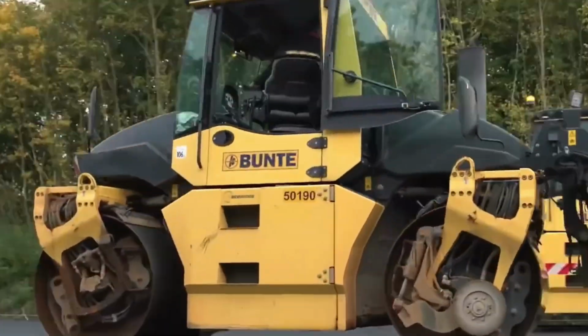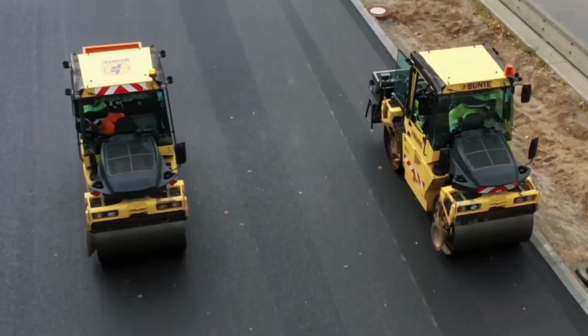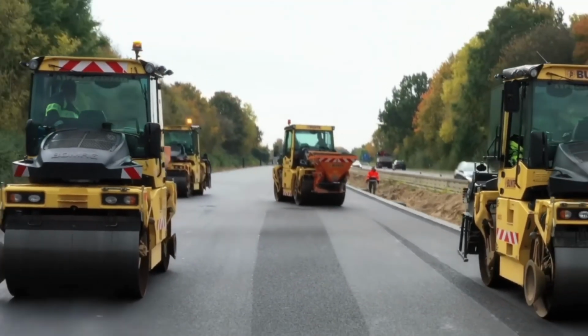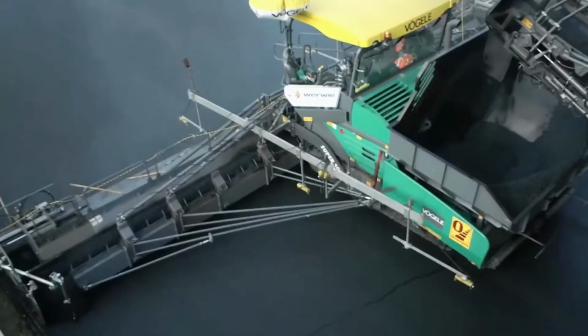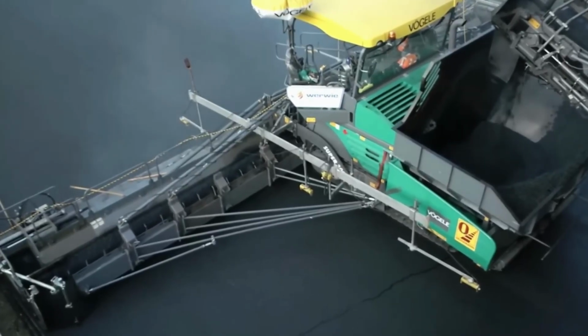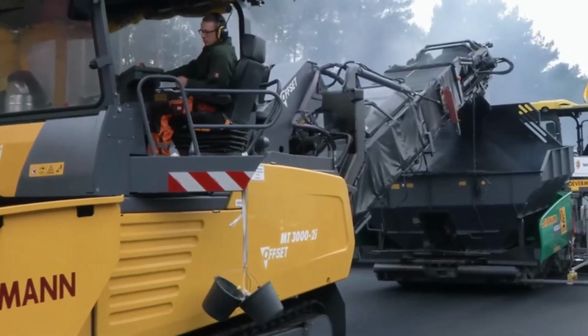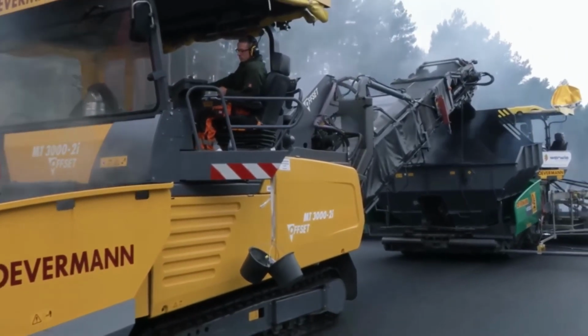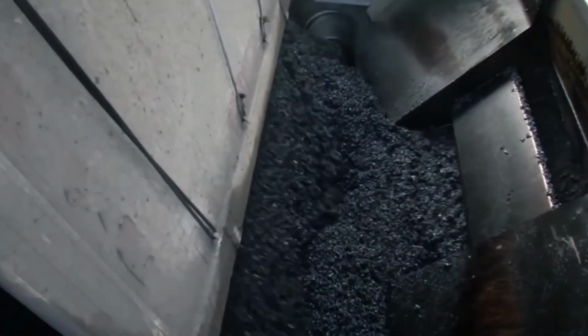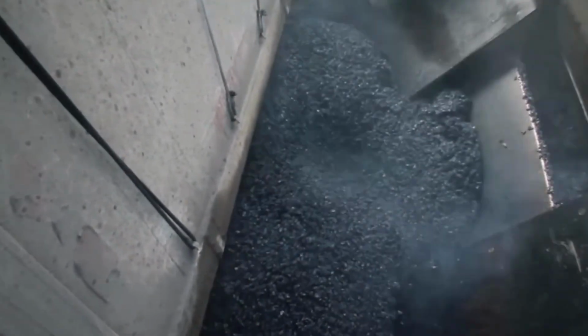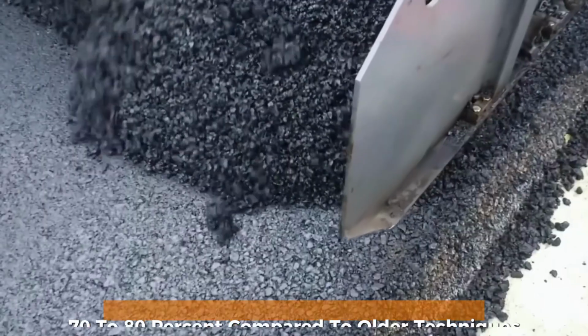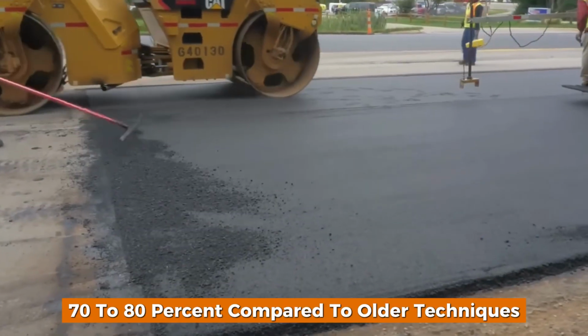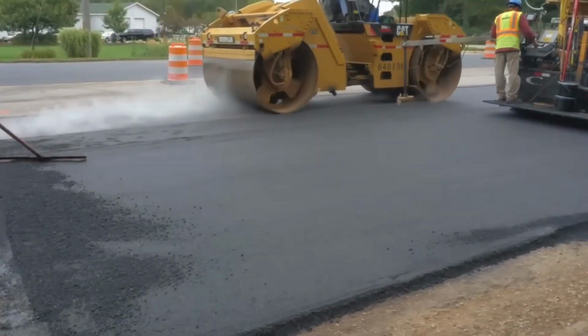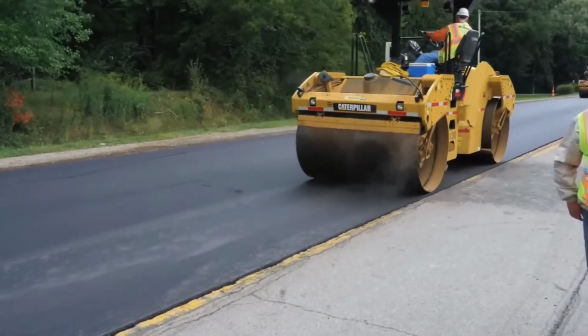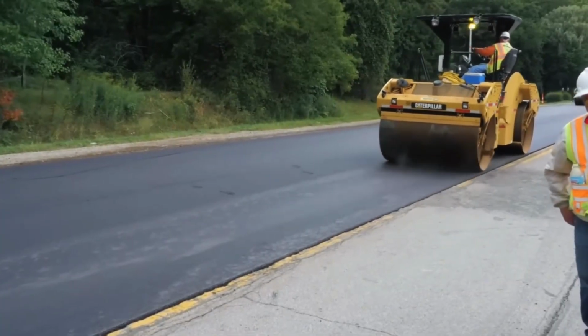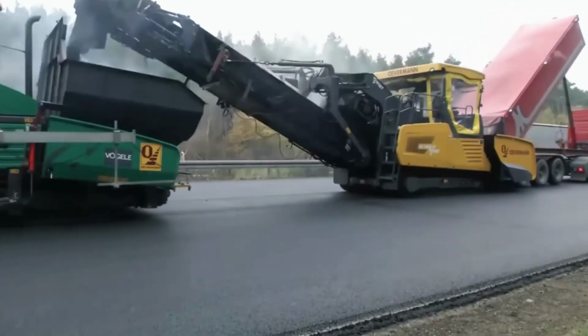In earlier decades, crews relied on multiple rollers, vibratory, static, and pneumatic, to reach proper density. Today, advanced asphalt pavers perform more than half of the compaction internally, reducing reliance on heavy roller passes. Vögele pavers from the Wirtgen Group are widely recognized for their precision, material efficiency, and ability to reduce roller work by 70 to 80% compared to older techniques. After paving, a light steel roller may complete a final pass, though many projects skip this step because the surface already meets specifications directly out of the machine.